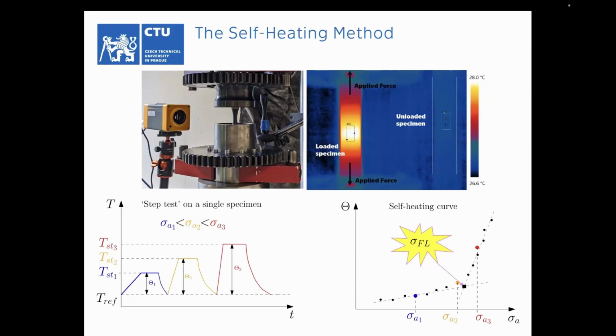Why is the self-heating method a rapid means of evaluating the fatigue limit? It's because the stabilization of the temperature occurs after usually several tens of thousands of cycles. So we can run what is called a step test on a single specimen, loaded in blocks with different stress amplitudes, wait for the temperature to stabilize, and here we have enough data to find this diagram.